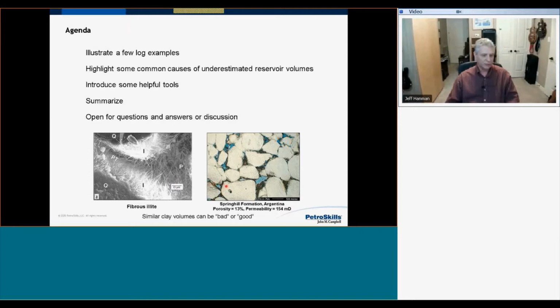A similar volume can actually be good in the case of clay coats on these grains that may inhibit further cement precipitation, further growth into the pore space, and actually preserve permeability. So in this case, this rock has only 13% porosity, which is good for a lot of people, maybe not so good for others, but the permeability is great for everyone, 154 millidarcy. So what we'll talk about is the volume of clay is only part of the answer. Where the clay lies, its morphology, its distribution is more important probably than the volume. And the main takeaway is that if you take nothing else from this today, look at your pore systems. That's really the most important message. If you don't do it routinely, please do it. For any interpretation of complex pore systems, it's really critical.